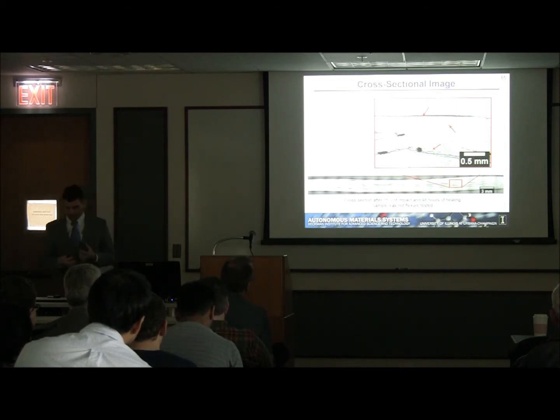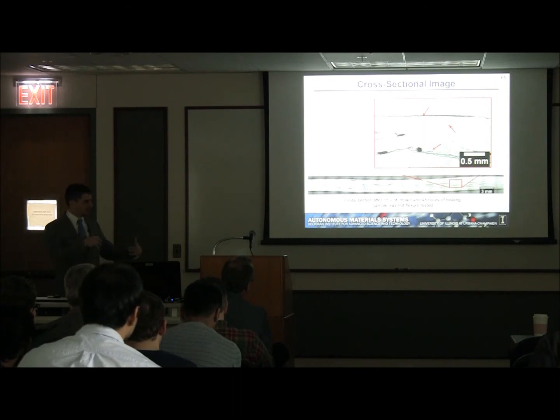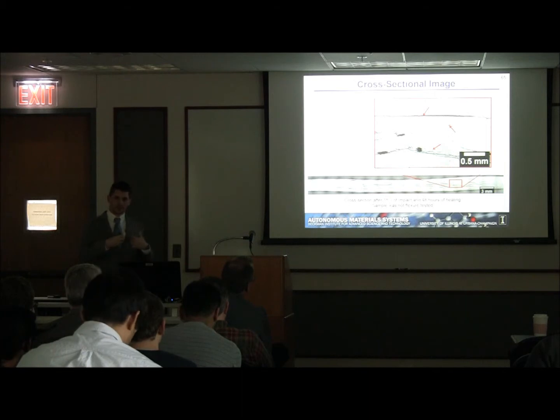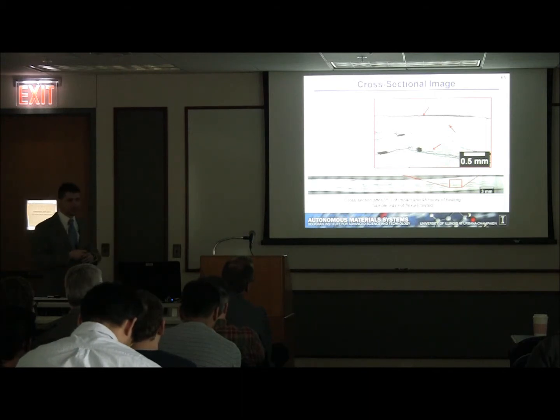And we think that this has to do with some of the damage connectivity issues, and that we have a segregated area of damage which does not have a connection with the microvascular network to receive healing agents. We cannot heal those damaged regions.